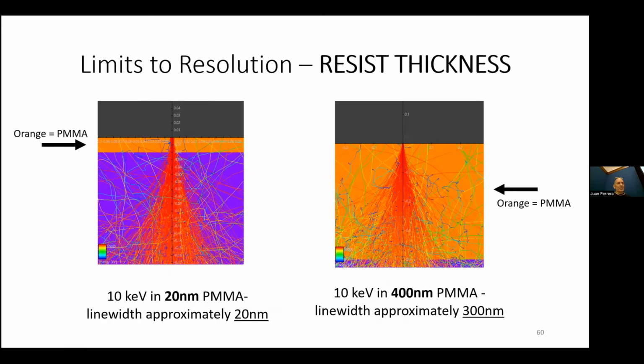So this is looking at the same sort of point spread function, but from a different viewpoint. If we want to have high resolution and we have thin resist like this, like 20 nanometers of PMMA, then we'll get a fairly small spot size. On the other hand, if we have 400 nanometers of PMMA, and this is all being done at 10 kilovolts, then we're going to get a huge spot size, like 300 nanometers instead of 20. I use these lower voltages because they illustrate the point more dramatically.